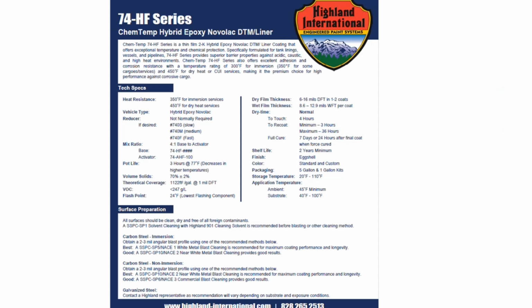And this is a 74HF series. This is a standard epoxy novolac DTM liner. Once again, we use this for chemical immersion, as well as CUI up to 400 degrees. It's a coating that goes on from 6 to 16 mils. As a standard novolac, you don't want to build these much more than 25 mils because they start to become brittle. And that's where you'd have issues with cyclic service or that thermal shock if you build these too thick. That's one of the cons with these products.